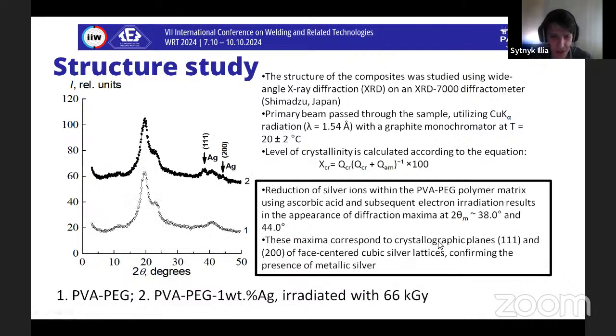During the reduction of silver ions in the PVA PEG polymer matrix with the help of ascorbic acid and cross-linking of the sample by electron irradiation, two diffraction maxima at 38 degrees and 44 degrees appear on its diffractogram, which correspond to crystallographic planes of the face-centered cubic silver lattice, characterized by indices 111 and 200, respectively, and confirm the presence of metallic silver in the polymer system.